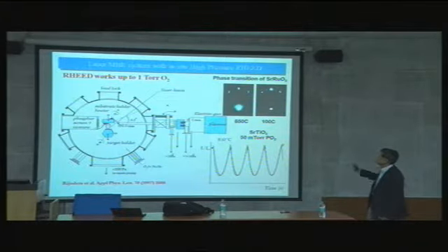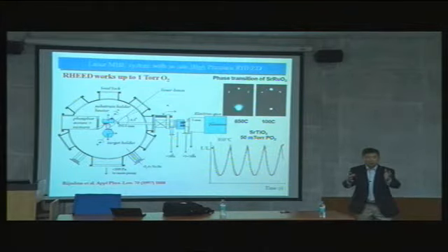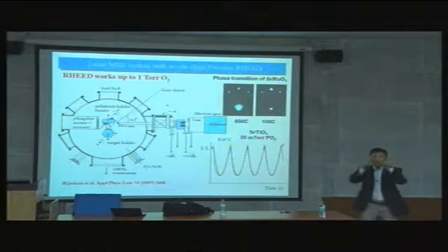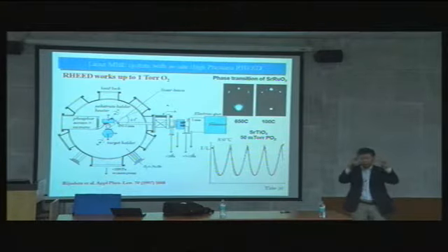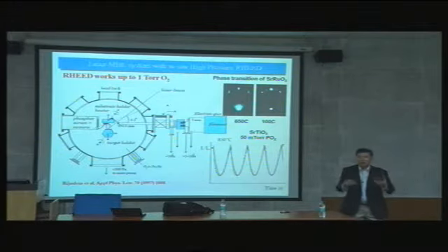But outside here, where the laser beam comes from, you have to bring the laser in first. Then you have to make a beam profile, a very uniform regional beam profile, because your atomic flux and composition all depend on the local energy density on the target. When I want 1 joule per square centimeter energy density, that means the average energy density, but different regions have different energy densities.